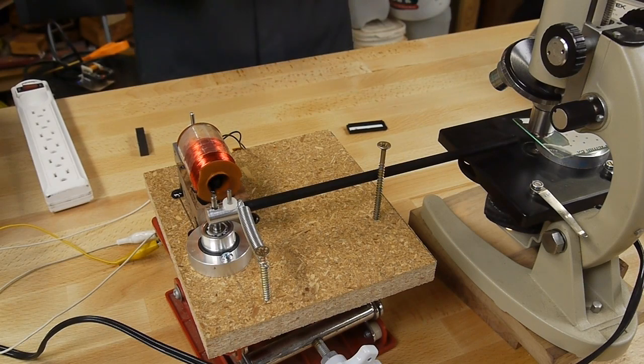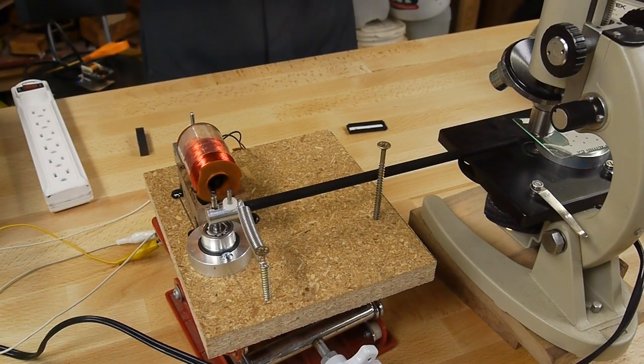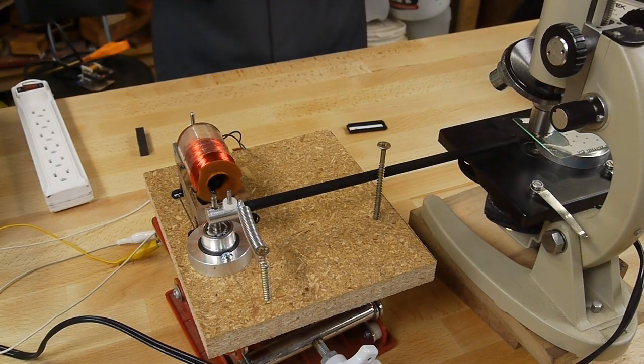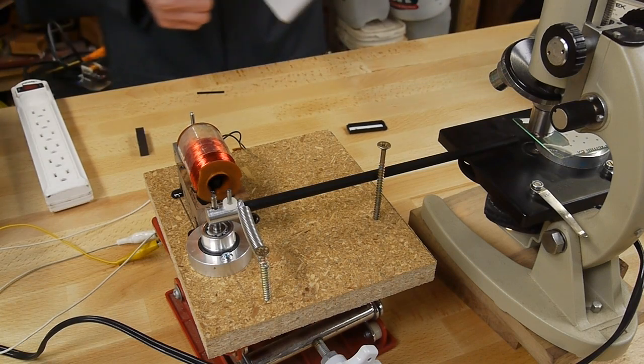Also, just to show how sensitive this setup is, the thermal effects - a piece of metal expands when it gets warm - and so this is me just breathing on the strip. You can see that the effect of just a tiny amount of breath touching it, I wasn't right on top of it either, it's just a little bit, is way bigger than the effect caused by magnetostriction. Then just for kicks, I got some freeze spray out and hit it with that, and you can see the pointer went off the screen because it was just a huge change in comparison.